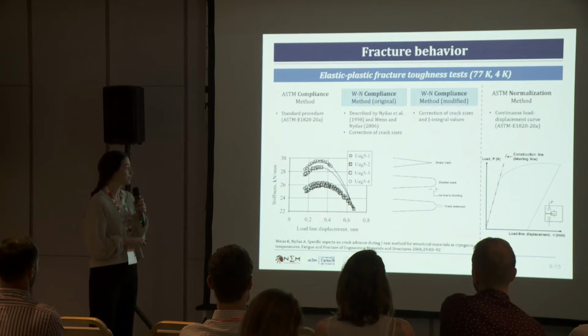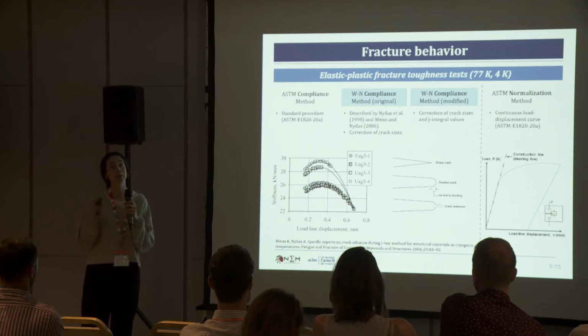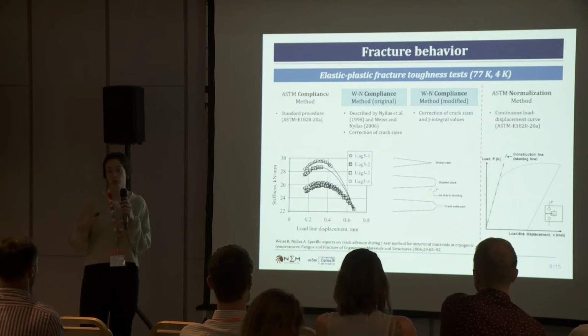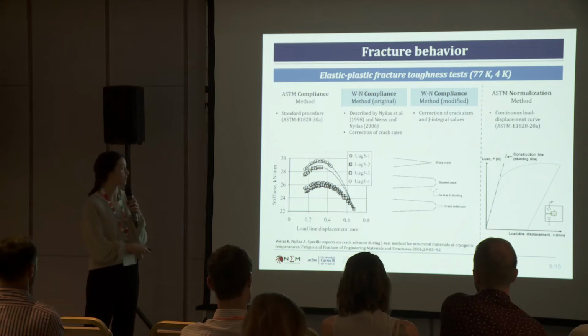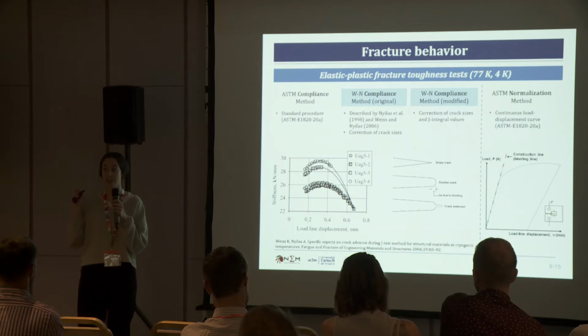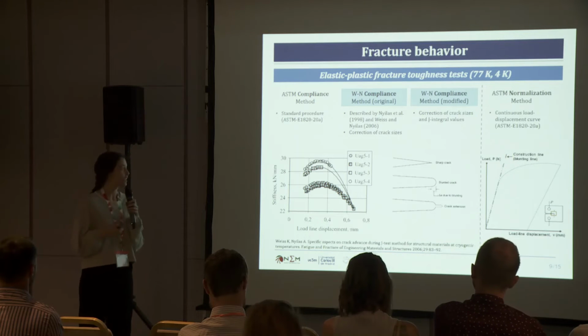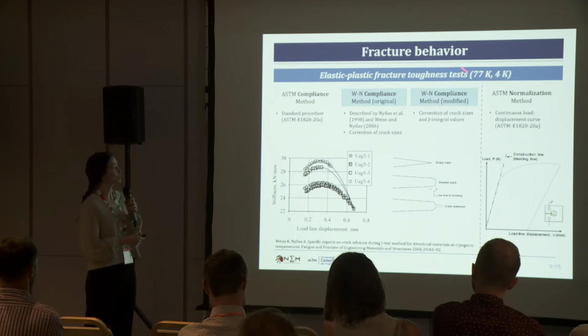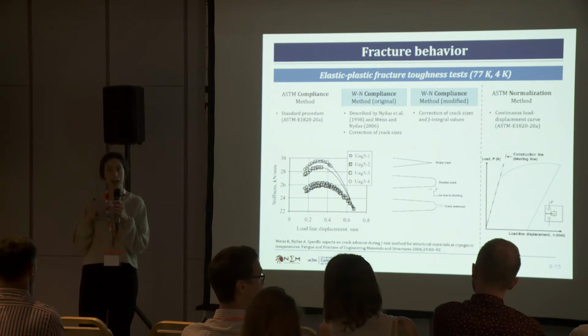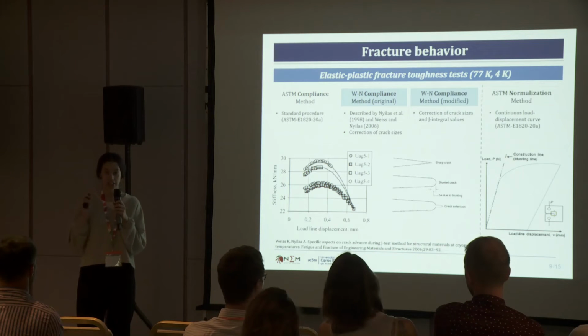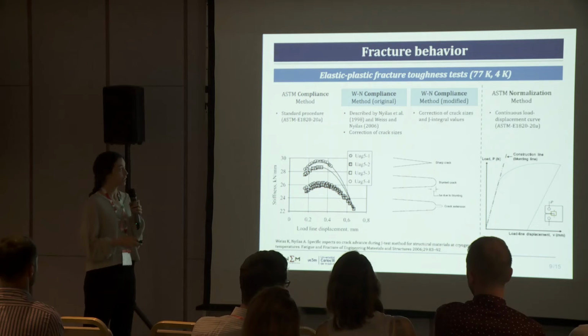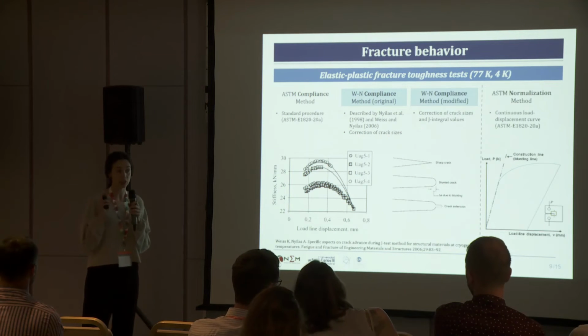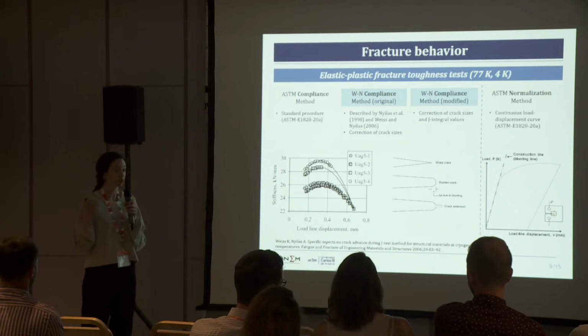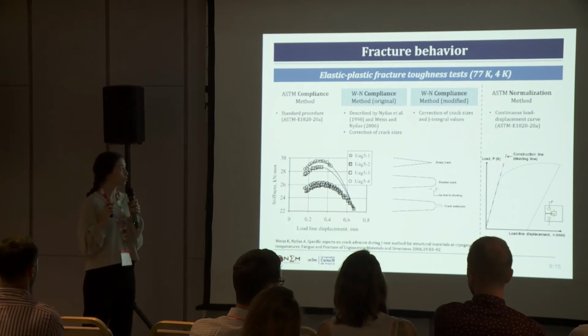So according to them, this phenomenon, the apparent negative crack extension, is coming because there is some strain hardening in the plastic zone ahead of the crack tip during blunting. So they did propose a method, I'm not going to go here in detail, to correct this phenomenon, and also to correct the crack sizes, because it's not always super well estimated with the compliance. So this is the original version of this method, and we have then the modified version. This one, we have proposed it. And it's exactly the same as the original one. We are just adding an extra step, that is the calculation of the J value based on the corrected value of the crack sizes, because the J value is a function of the crack size. So we thought that it's more accurate to recalculate it using the corrected values. So that's all. Those are the 4 different methods.